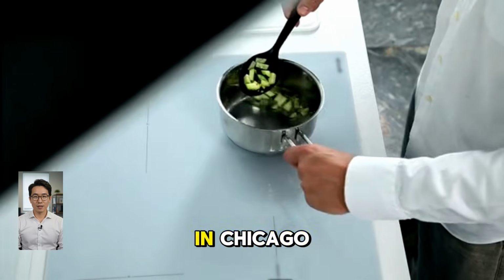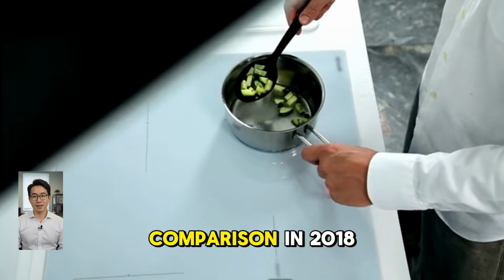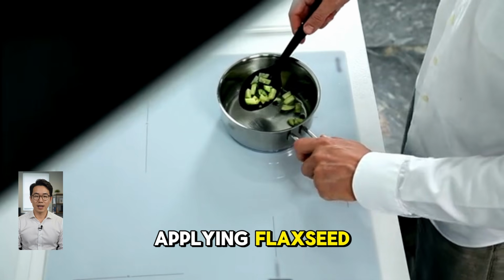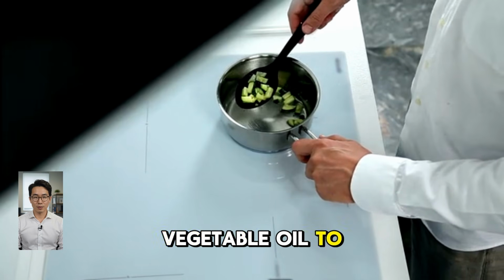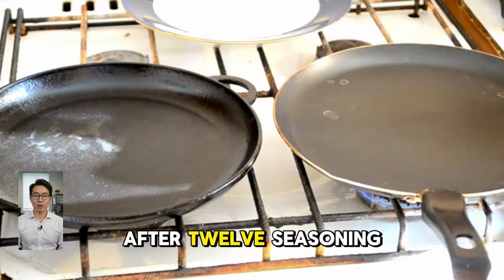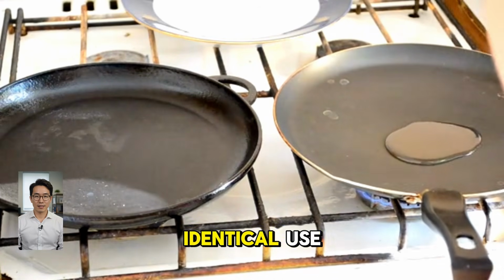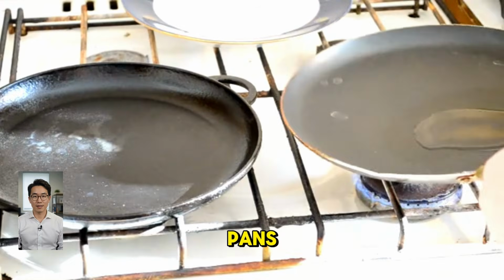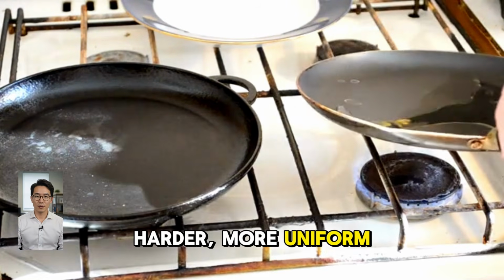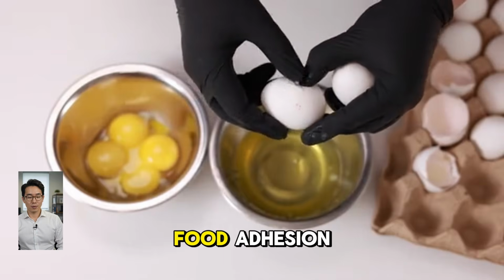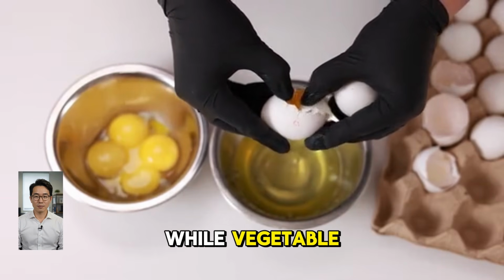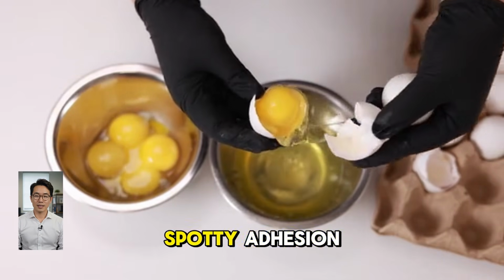A culinary instructor in Chicago documented a head-to-head comparison in 2018, applying flaxseed oil to new skillets and vegetable oil to an identical set. After 12 seasoning cycles and 3 months of identical use, the flaxseed oil pans showed a visibly darker, harder, more uniform surface. They produced lower food adhesion scores in egg tests, while vegetable oil pans showed persistent, spotty adhesion patterns that had